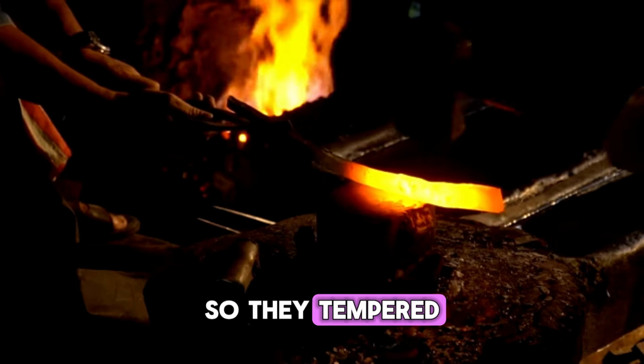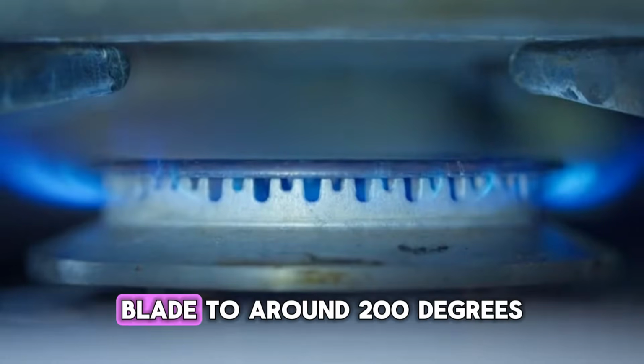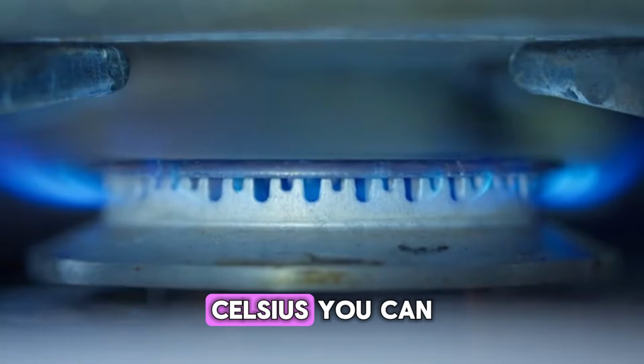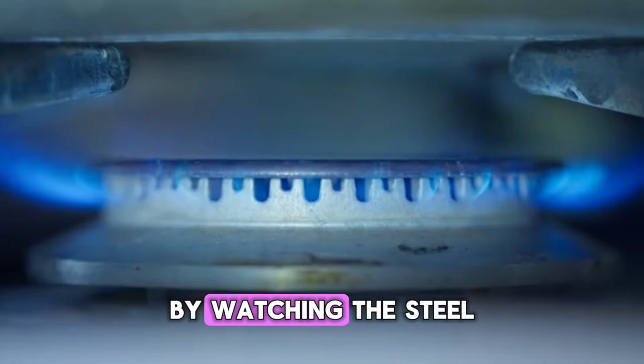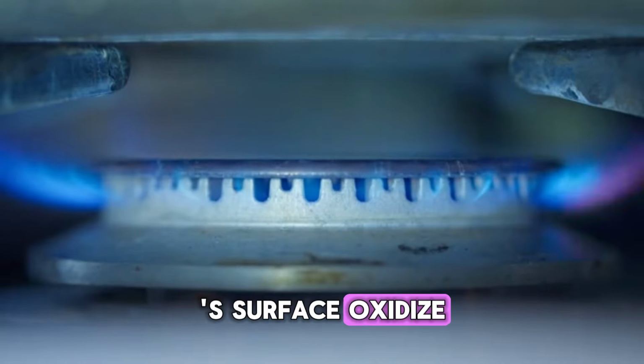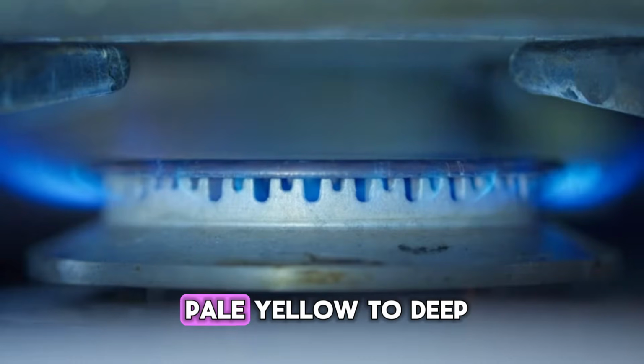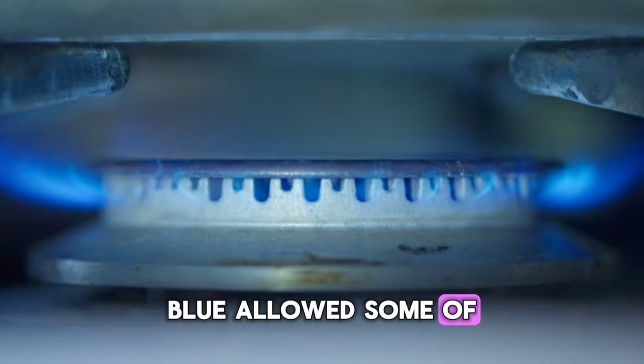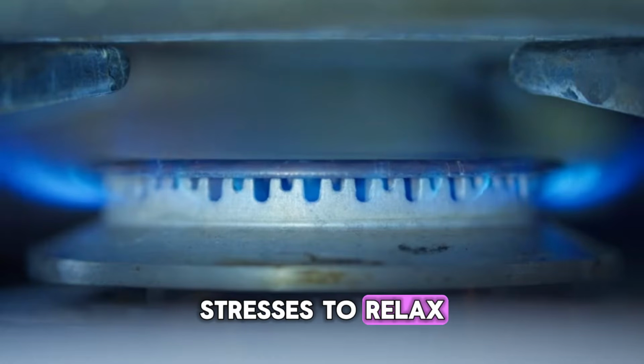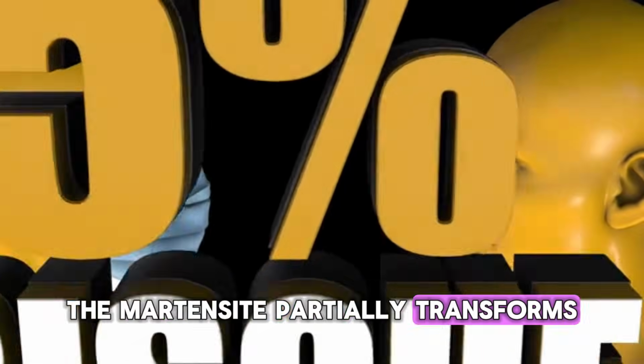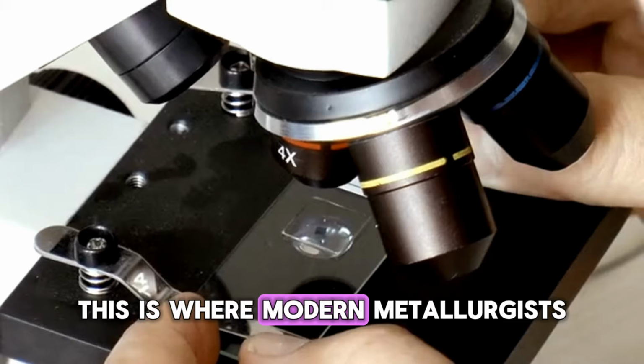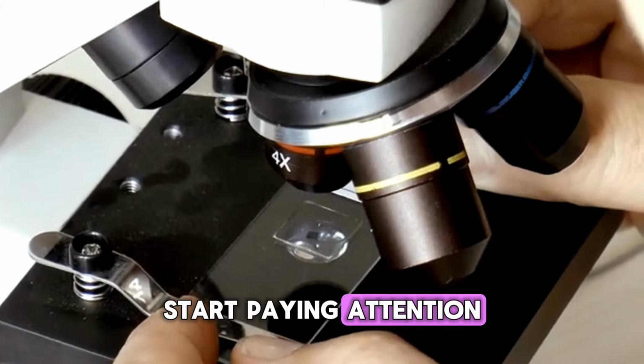So they tempered. Reheating the quenched blade to around 200 degrees Celsius, you can judge the temperature by watching the steel's surface oxidize through a spectrum of colors, from pale yellow to deep blue, allowing some of the internal stresses to relax. The martensite partially transforms into tempered martensite, trading some hardness for desperately needed toughness. This is where modern metallurgists start paying attention.